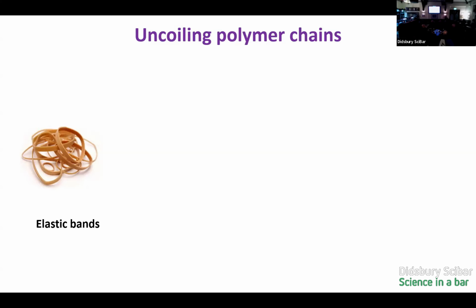But when we think about stretching an elastic band, essentially what we're doing when we pull this elastic band is uncoiling those polymer chains, okay? So when we have an elastic, when it's at rest, the polymer chains are in their coiled state. And when we start to put some force on them and pull the elastic band, we start to uncoil those polymer chains and start to pull them out. So if we think about, again, coming back to our paper clips, this isn't great, but you can see we have effectively an uncoiled random bit of our polymer. And then when we start to pull it out, we start to stretch out that coil and we start to stretch the polymer chain. And that's what happens when we're stretching this elastic band.